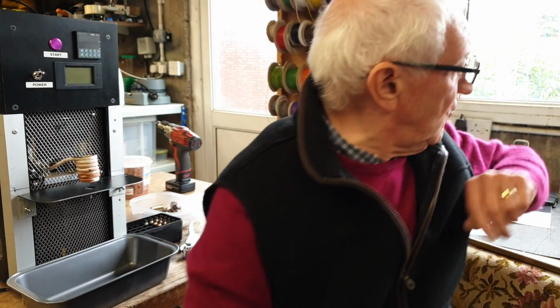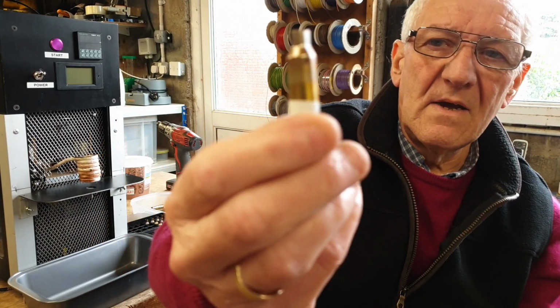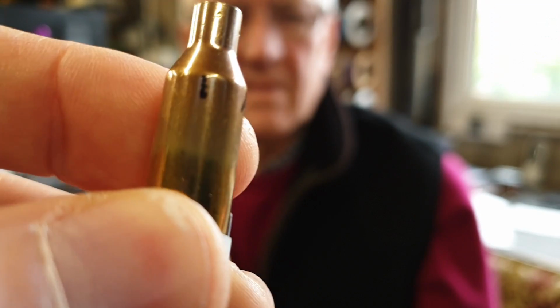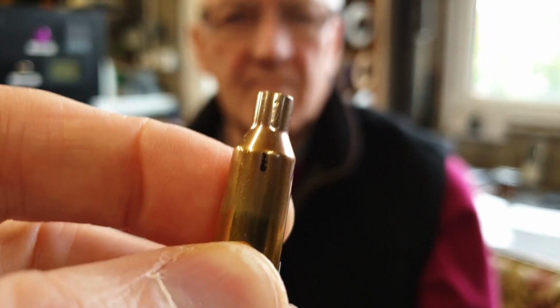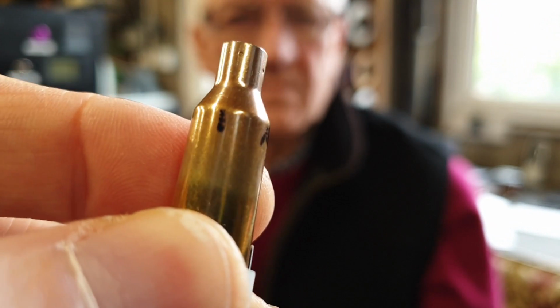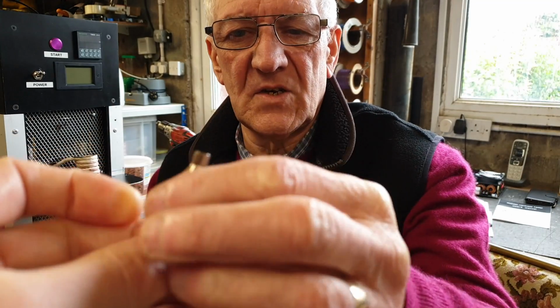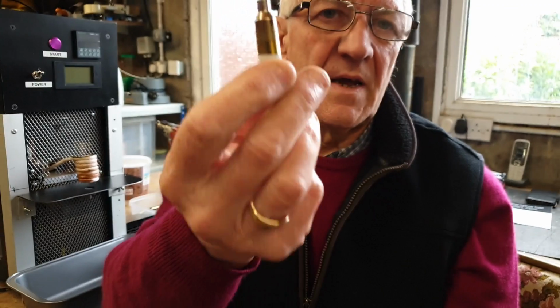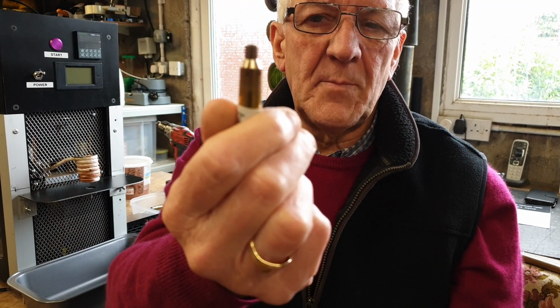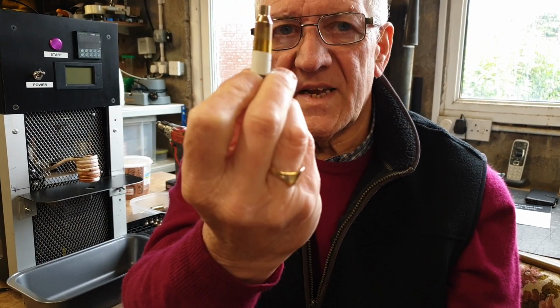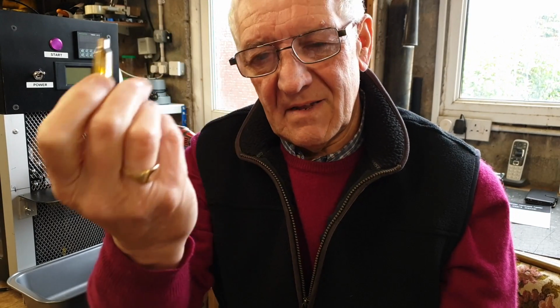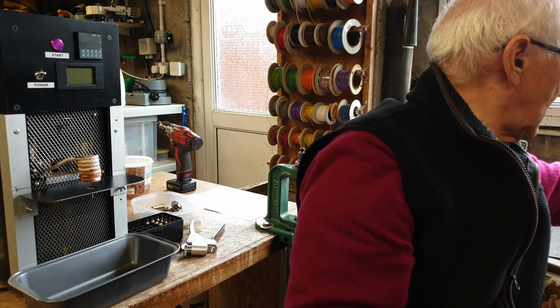So the surface colour change, when you see annealed brass, like this brand new Lapua brass, you can see there's clearly a colour change. Just above my thumbnail, you can see the colour change from there up to the end of the brass case. That colour change is what a lot of people use to decide whether something's been annealed or not. The problem is that with this salt bath method, you can put the cartridge into the molten salt, leave it for 5 seconds, pull it out, and it looks like that. But when you hardness test it, it's still hard. It hasn't softened. That was a major deal for me in deciding that I'm not going to go down the salt bath method.